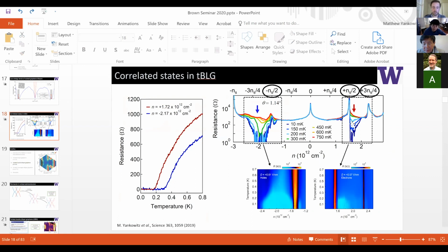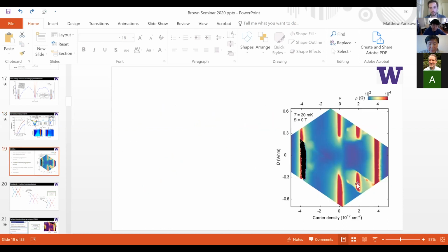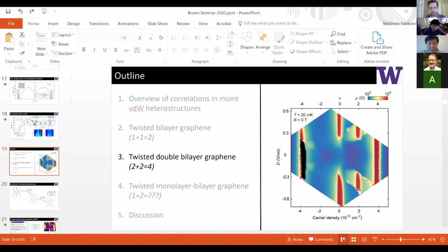I see. But those don't have the required net Berry curvature to yield an anomalous Hall effect. Right. It's difficult from a transport perspective to be sensitive to the anomalous Hall effect when the Berry curvature integrates to 0. Right. But could they be valley anti-ferromagnet? I think in principle, yes. So these states in twisted double bilayer graphene, which we think are spin polarized or spin ferromagnet, would likely be valley anti-ferromagnet. Huh. Well, that's very interesting. Thank you.